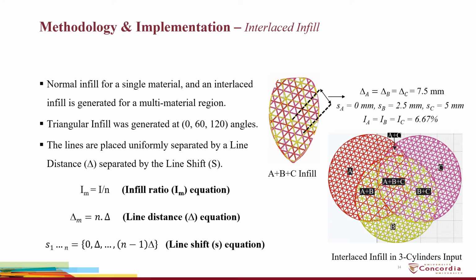Using the material information of material regions, we developed an interlaced infill pattern for our 3 cylinders input model. For a single material region like region A, we generated single material triangular infill. And for a multi-material region made of A, B, and C material, we generated a multi-material infill. In case of multi-material regions, the infill of a region is divided between the materials forming the region, and the infill lines are arranged in a staggered manner using the line distance and line shift parameters. The value for these parameters are calculated according to the mentioned equations.